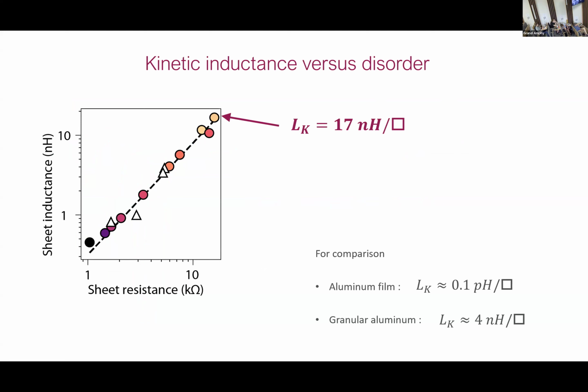These are examples of values that we extracted in our work for indium oxide, but you have more or less the same for nitride if you approach the superconductor-insulator transition, and you see that you can reach a huge number. So nanohenry perhaps doesn't give you much information, but it's very large. If you want to talk about impedance, for instance, if you make microwave circuits and a microwave resonator, you can very quickly reach regimes where the impedance of your resonator is above the quantum of resistance. But do you expect it's still valid in this limit?